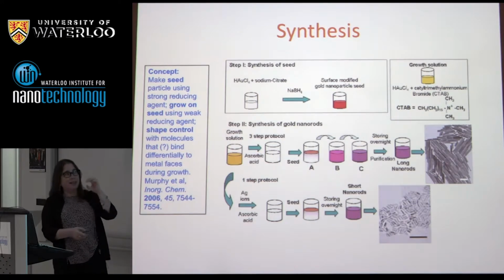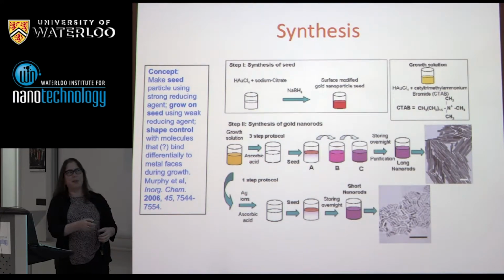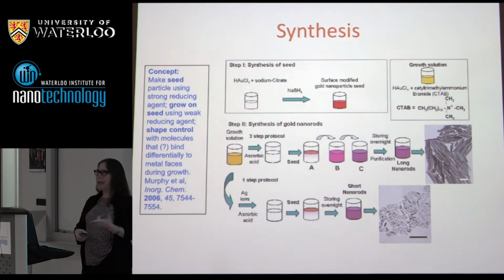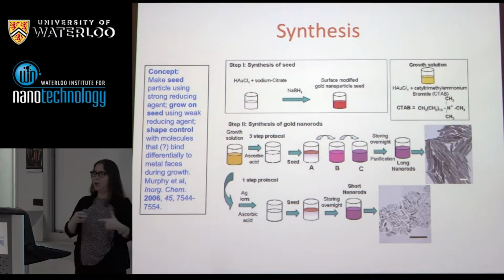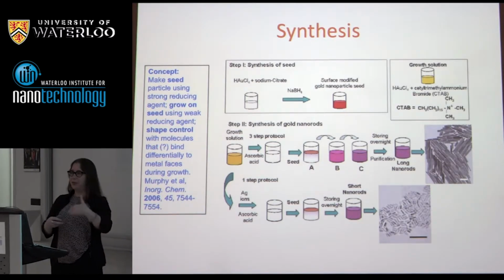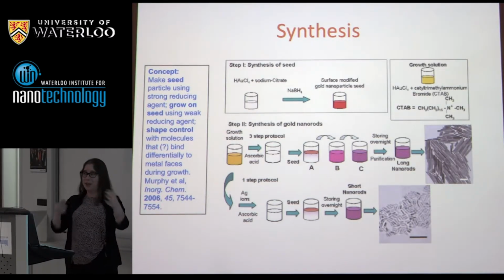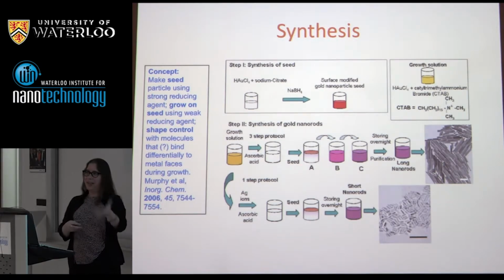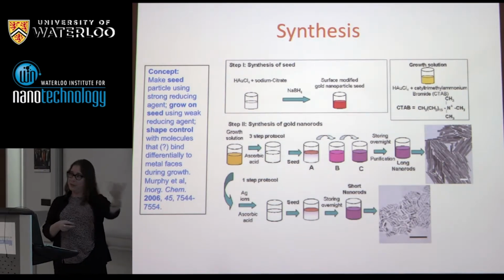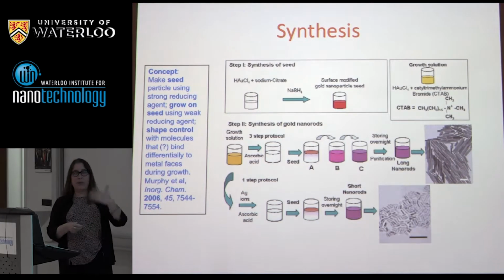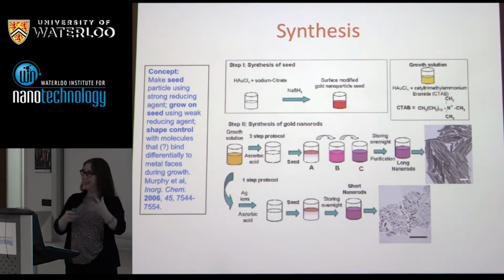Okay. So then we take them out, put them in a fresh pot with more metal salt, and now a weak reducing agent, ascorbic acid, coming up here. The idea is that ascorbic acid at room temperature doesn't have the thermodynamic juice to reduce gold-3 to gold-0. So we don't want to make new seeds. We want to grow on the existing seeds, and the redox potential of a surface-bound species is different from the free solution. So we will autocatalytically grow on the seeds, is the idea.